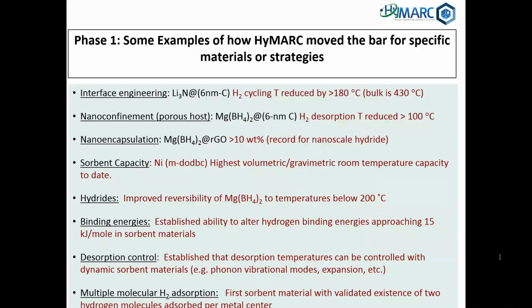And so we've tackled a number of different strategies, and I'll show you just a few of them listed here. Metal hydrides in particular, their complexity has been a steep hill to climb, but we've been looking at various strategies that can help us improve the thermodynamics and kinetics. An example of that is our efforts to probe the interfaces between hydrogenated and dehydrogenated materials. This has resulted in some cases where we've had really remarkable reductions in the heats of desorption required. Lithium nitride is an example where our understanding of the nanoscale effects of these interfaces allowed us to reduce the cycling temperature by over 180 degrees C.